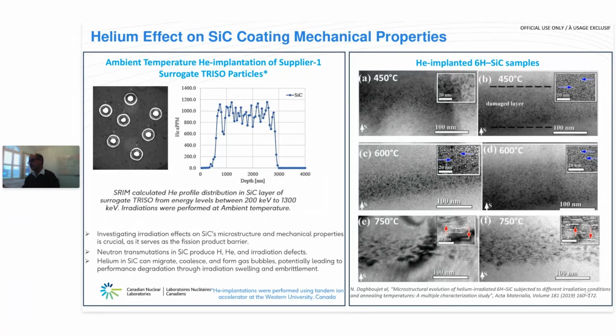On the right, what you see are literature results where helium implantations were done in 6H silicon carbide single crystals at different temperatures. Because of the helium, you start to see some nanobubbles forming within the material at 450 degrees C and at 600 degrees C. And at 750 degrees C, these bubbles become elongated in shape and were extremely big.